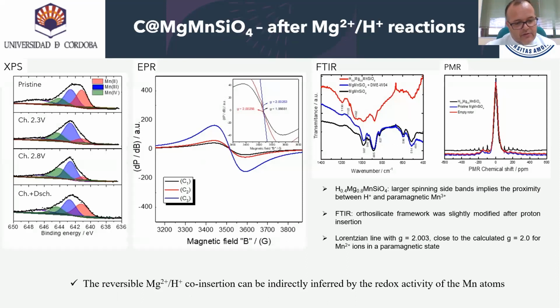XPS assessed the manganese oxidation state at the manganese 2p core levels. Overall, magnesium extraction is evidenced by the expected higher binding energy shifting after charging and discharging. The significant contribution of trivalent and tetravalent state in the original sample must be ascribed to some unavoidable oxidation of the particle surface. On partial charge and eventually full charge, the relative contribution of manganese 3 and manganese 4 significantly increased, as we can see here, manganese 3 in blue, manganese 4 in green.